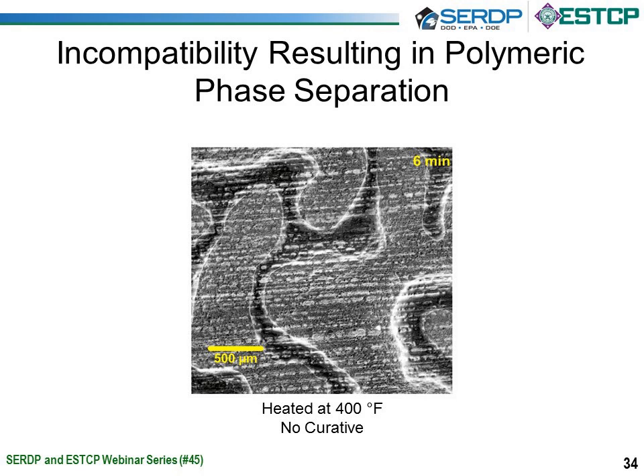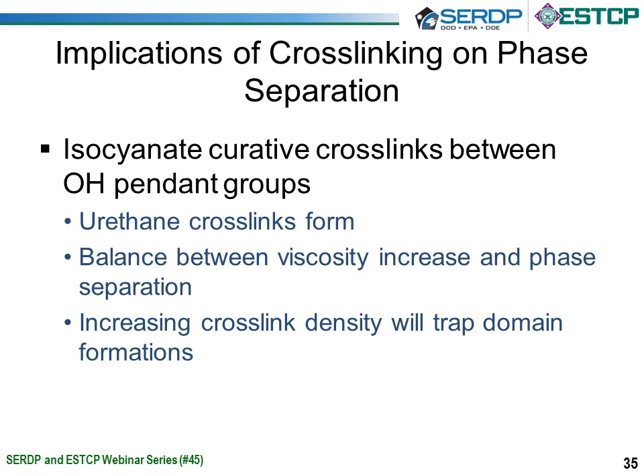In slide 35, we wanted to utilize this incompatibility and cross-link these high and low OH polyols into a durable urethane system. In order to do so, we selected isocyanate as our curative because it's frequently commercially available and has been utilized in many commercial applications to cross-link polyols. In this particular case, we used a commercial ε-caprolactam polyisocyanate, which will afford the desired urethane cross-linking. We selected the urethane because it was reactive with the polyols and also would afford a very durable, chemical-resistant coating.